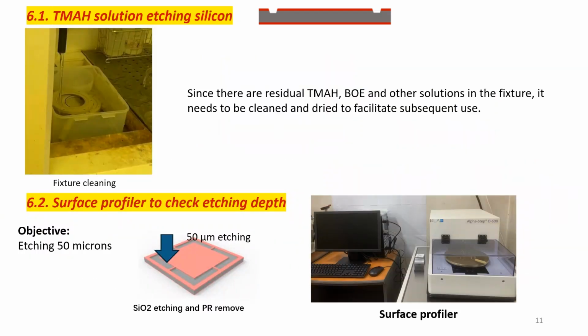Since there are residual TMAH, BOE, and other solutions in the fixture, it needs to be cleaned and dried to facilitate subsequent use. Then we use the surface profiler to check the etching depth. Our objective is 50 micron. We measure 9 locations on the wafer and find that the etching depth is relatively uniform, about 54 micron. The result basically meets the requirement.